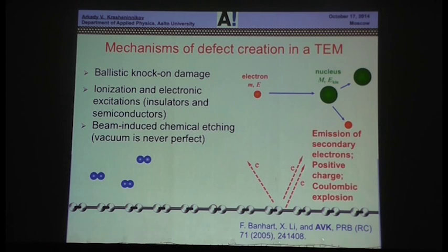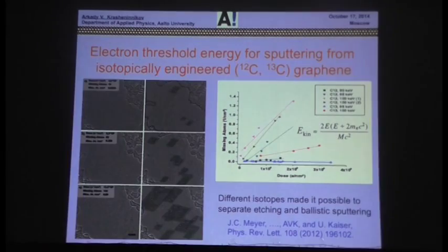Vacuum is never perfect. You always have lots of junk in your chamber: water molecules, oxygen molecules. The electrons break up the molecules, for example creating individual oxygen atoms, which are quite reactive, and they may etch your sample. You may ask me, is there any evidence that this mechanism really works? Knock-on damage is obvious, but as for the others, recently my co-workers did a very cute experiment. They actually grew graphene from carbon-13. This means that the chemistry is exactly the same, but the mass of each atom is different, it's heavier.